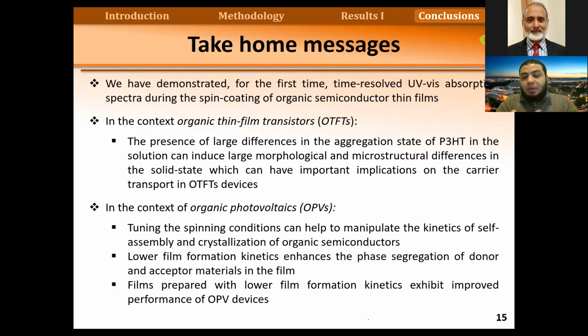So the take-home message from this: we have implemented a new technique, for the first time, to get time-resolved UV absorption during spin coating, and we have applied this to two different categories of application. One is thin film transistors for a single component, the P3HT material, and also solar cells. What we have found is that if we have a large difference in the aggregation state in the solution, we can affect the formation dynamics and the aggregation dynamics of the polymer, and this will affect the final product. And also for the solar cells, if we change the dynamics, we can tune the final microstructure and the crystallization in the final film, and this also has implications for the solar cell performance.